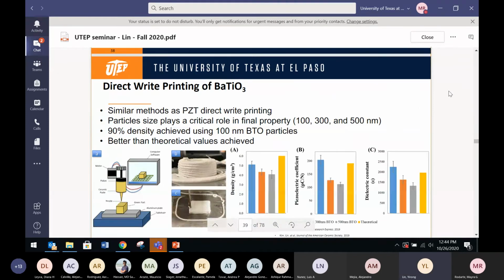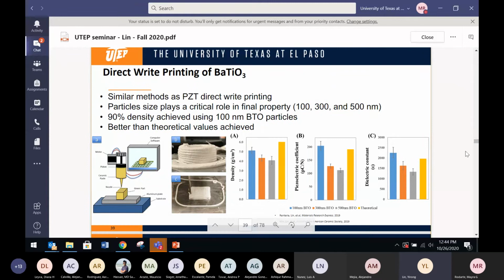Okay, so we started with preparing the slurry. In this case, you're just mixing these ceramic particles, in this case nanoparticles, with polyvinyl alcohol, which is a polymer, and you add water in, then you can make a slurry, very similar to toothpaste, but probably more viscous. And then once you go through a syringe, you can print that out, either a cylindrical shape or a square shape. That's pretty easy to do, right?